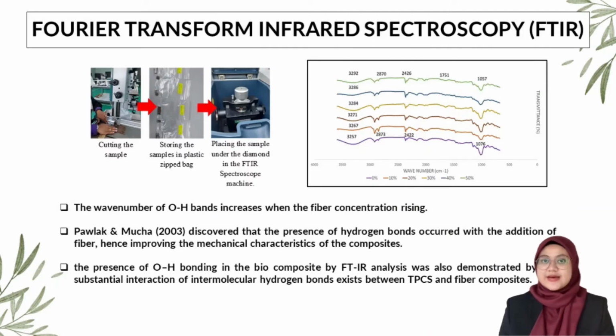The FTIR analysis result shows that the wave number of OH bands increases when the fiber concentration rises. A study by Pawlak and Mucha discovered that the presence of hydrogen bonds occurred with the addition of fiber. Hence, it improved the mechanical characteristics of the composites. The presence of OH bonding in the biocomposite by FTIR analysis was also demonstrated by the substantial interactions of intermolecular hydrogen bonds between TPCS and fiber composites.